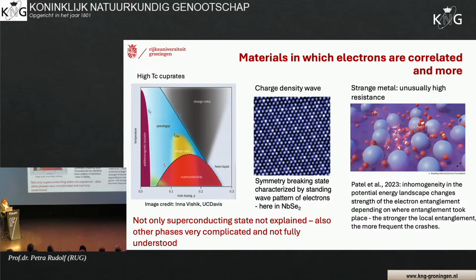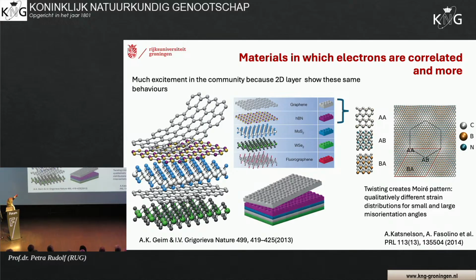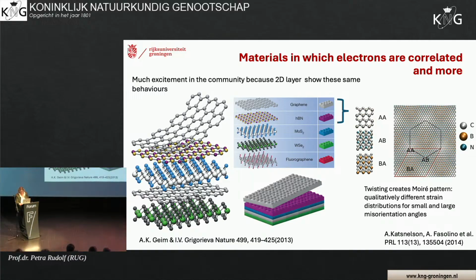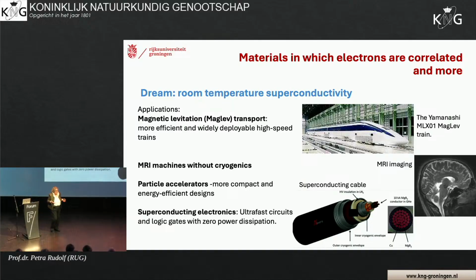And what helped us a lot in describing that is that now we can make artificial solids, because we take just one layer. It started with graphene that you peel off with Scotch tape from the graphite, and you put it somewhere else. And the same we can now do with a lot of layered structures, and we make solids where we decide how we combine them. And from this we have understood more and more things about how they interact. The dream is to really understand this better in order to get to superconductivity at room temperature. Yeah, we are still 100 degrees down, more or less. Sometimes there are claims that we get closer, but it's still difficult because we don't really understand how it works yet.